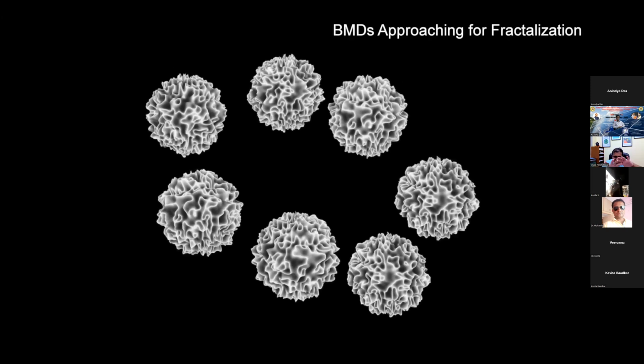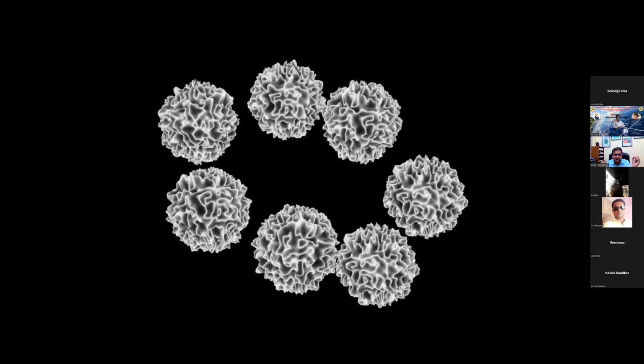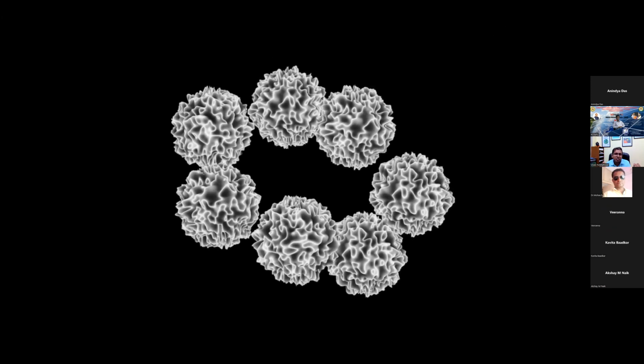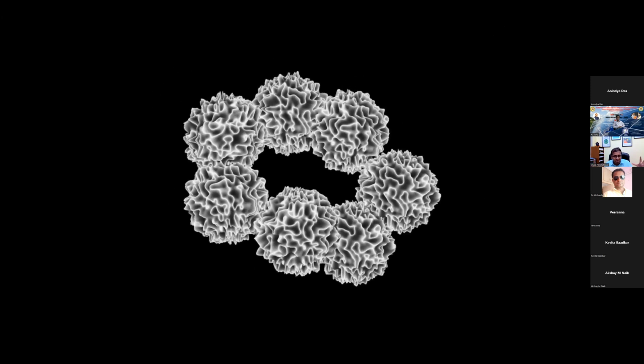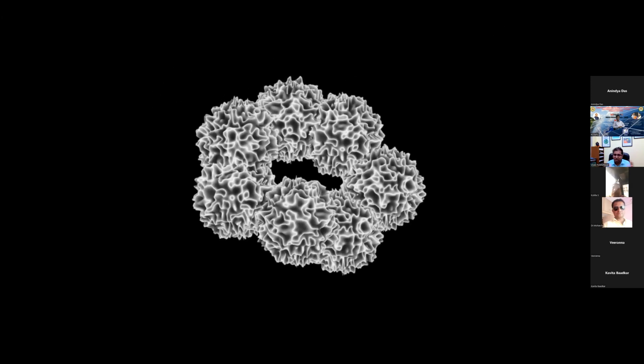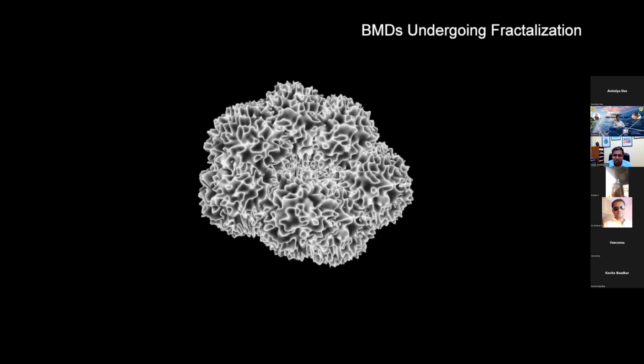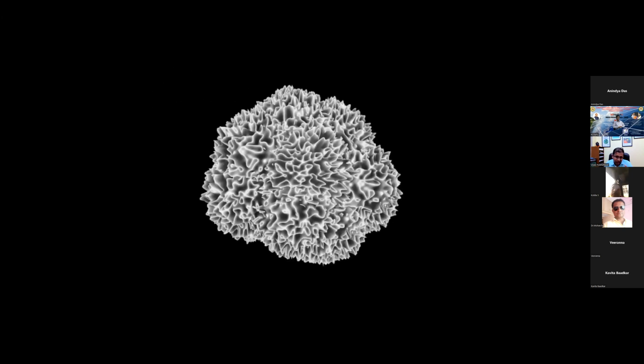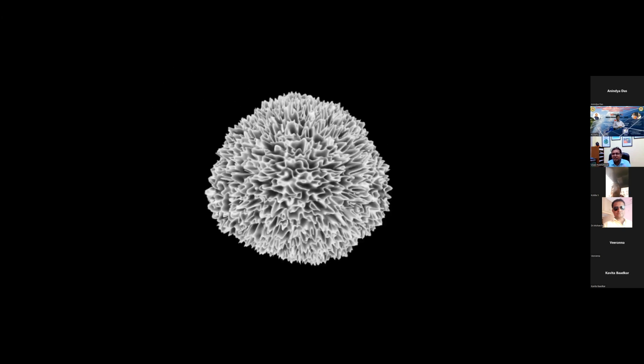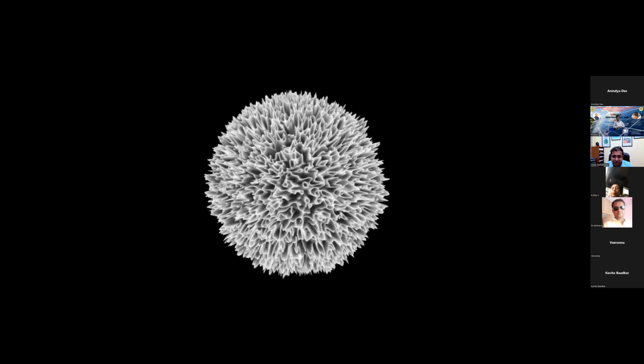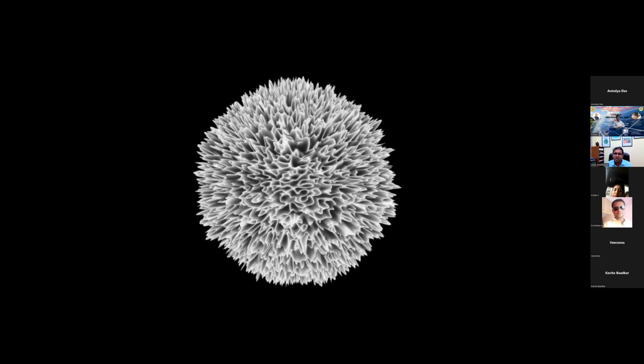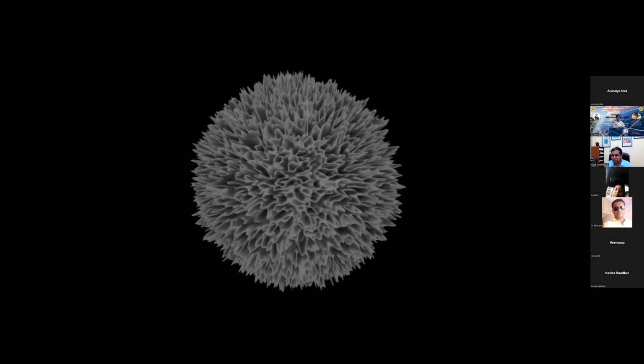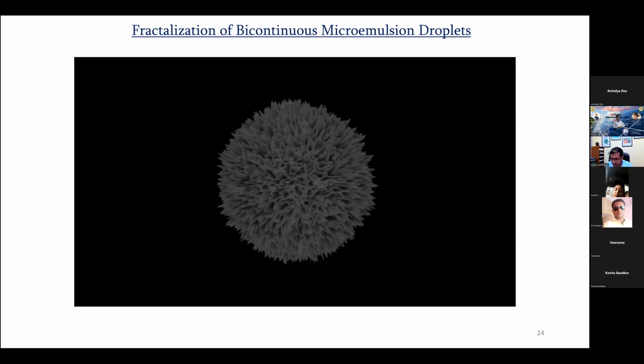So if I keep these droplets away from each other, you get a smaller DFNS particle, a smaller silica nanoparticle. We also learn to merge these droplets together, so you get a bigger bicontinuous microemulsion droplet. If I grow the silica in these bigger droplets, I get bigger size nanoparticles. That's how we were able to tune the particle size, from 50 nanometers up to 1.2 micron, 1200 nanometers.